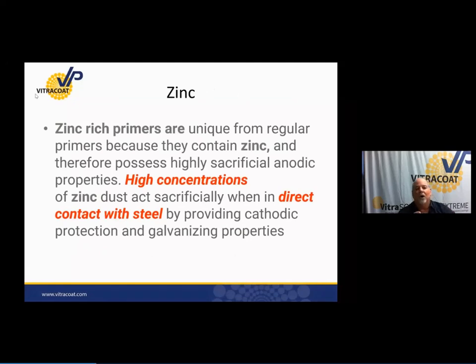Zinc-rich primers are unique from regular primers because they contain the zinc, and therefore they possess a highly sacrificial anodic property. High concentrations, and I've bolded that and made it red, high concentrations of zinc dust are sacrificial when in direct contact with steel by providing a cathodic protection and galvanizing property. So in order for a zinc primer to work, you've got to have enough zinc contained in the primer for it to work. Zinc rich didn't start with powder coating.